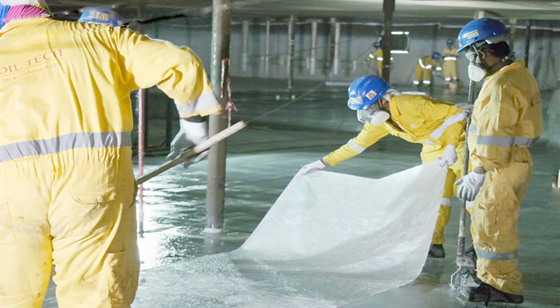The recent trend has municipalities shifting away from replacing tank bottoms and toward the application of fiberglass lining systems where recommended. Installing a lining system means applying a primer, catalyzed resin with a glass mat, tissue, and a seal coat. The tank must be dry and the surface properly prepared. The entire process is quicker and less expensive than replacing an entire tank bottom.